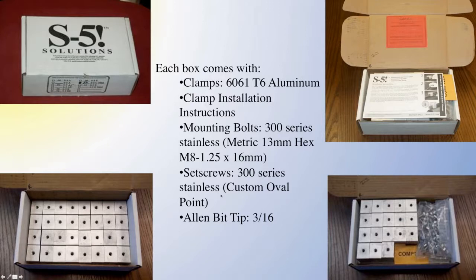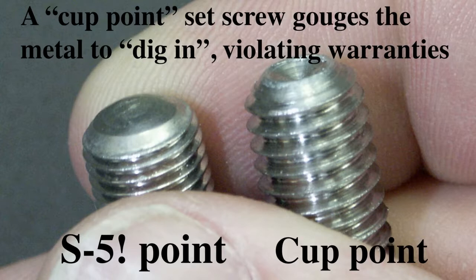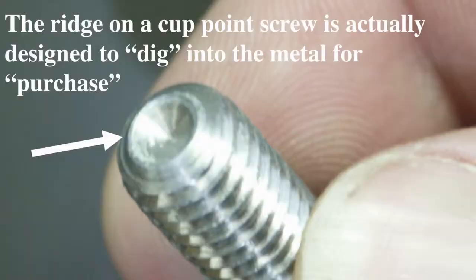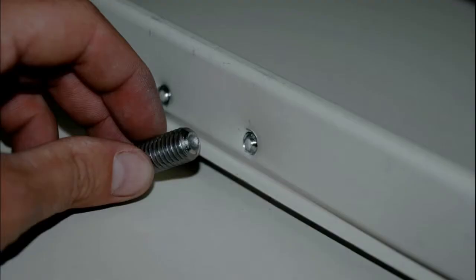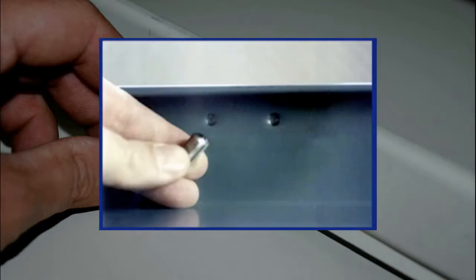The round point of S5 does not violate the thin, fragile coatings that I spoke of a moment ago, which provide the corrosion protection of steel roofing. And they do not cause fatigue fracture of other soft metals like titanium, zinc, and copper. Unlike a cup point screw, which breaches these coatings, violating warranties and creating a corrosion or fracture site. You can see the slight depression here made by the round point screw that creates a mechanical interlock without breaking the paint or metallic coating.